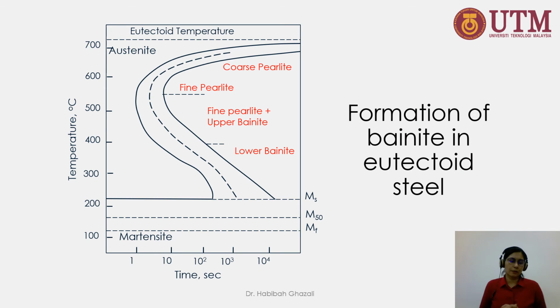Just by looking at those microstructures, we can predict that the bainite will be much stronger, or the strength of those materials will be higher compared to the pearlite, because the microstructure now will be much smaller, the needle shape, and also we have precipitation hardening happening for the lower bainite. So we have precipitates inside the grain of ferrite. So we can expect that this metal will be much stronger than pearlite.